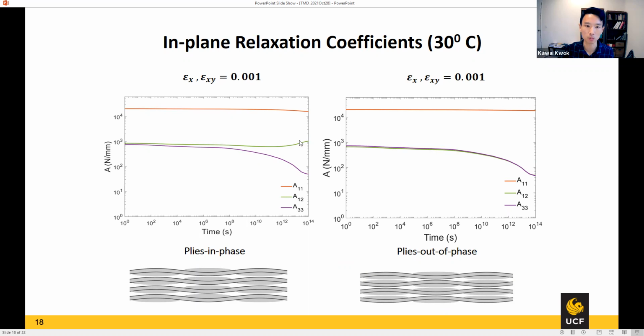So A12 is the coupling. If you stretch in one direction, what is the coupling stiffness in the transverse direction? The other two have no problem, but that is the only thing that caught our attention. We studied that by looking at two different extreme configurations that can happen. There are four layers of thin ply, and they're all in phase. We call them all in phase because all the V patterns are in sync. If you look at a different configuration where they're exactly out of sync, this is the out-of-phase configuration. And we do not see that upward trending of the coupling coefficient in the out-of-phase configuration.